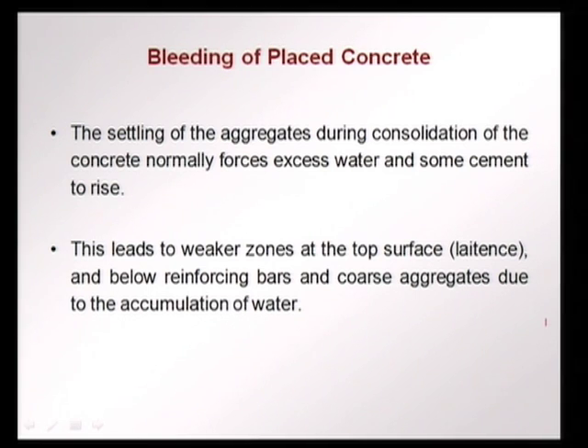We talked in several cases about bleeding. So, bleeding in placed concrete is the settling of aggregates during the consolidation due to compaction or by gravity. This forces the excess water upward, and along with this water some cement is also dragged upward. So, this leads to a top surface which is called laitance, and this sometimes you see on the surface of